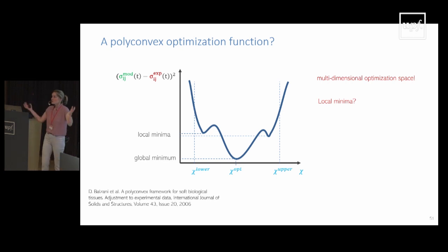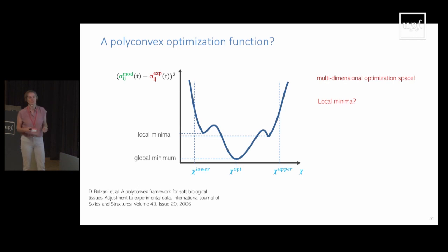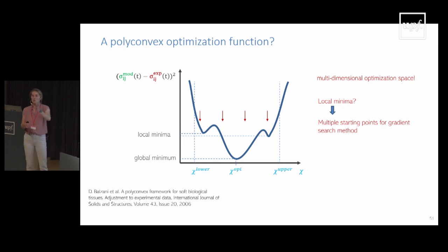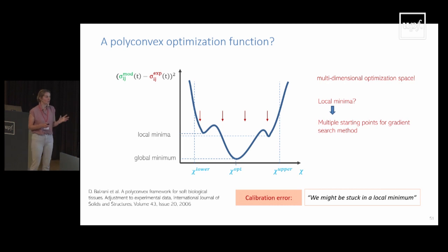Another thing that might go wrong is that your constitutive model is not a polyconvex function, which means that if you use a gradient-based search method, you might get stuck in some local minima. The way to solve that problem is to do your fitting multiple times and make sure that you use multiple starting points so that you can then find the minimum of all the minima that you found. Well, that is something that you should do, but of course, the more starting points you take, the more computationally intensive everything becomes, so you're adding on to the total complexity of your system. So you always need to take into account that you might be stuck in some local minimum.